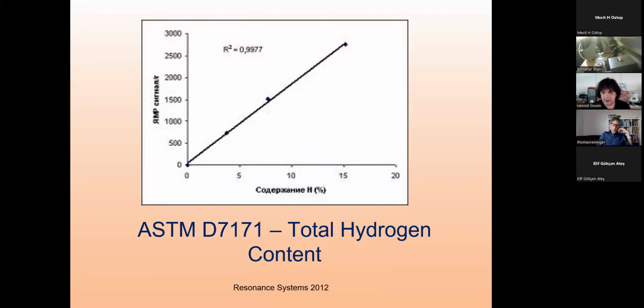Then I think the simplest application of time domain NMR is the total hydrogen content. You just look at all hydrogens that are in the sample, and you just see the intensity of the signal. You put fuel inside your tank when you drive the car or fly an aircraft. These hydrocarbons have different lengths, and hydrocarbons of different length have different hydrogen content. This method allows you, without using any high resolution NMR or any chemical procedures, to get the percent of hydrogen inside the fuel, and so you can get an idea whether your fuel is okay or not, depending on the number that you get.